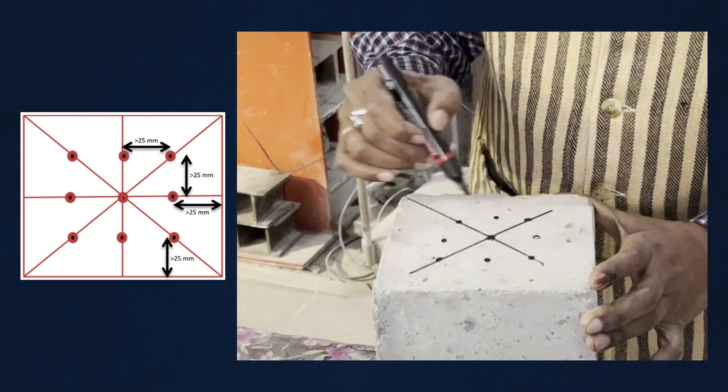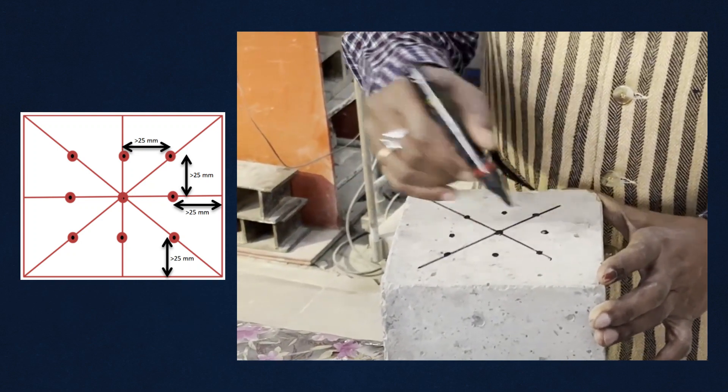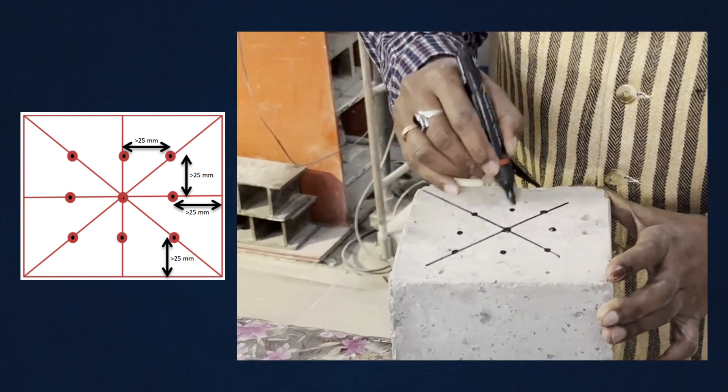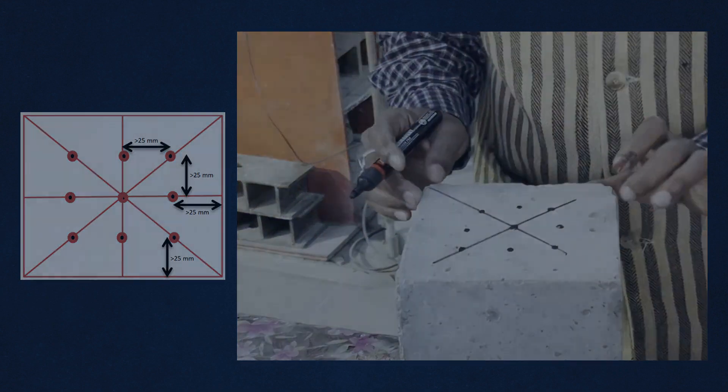Ensure that neither two points are nearer to each other by 25 mm, nor any point is closer to any edge by 25 mm.